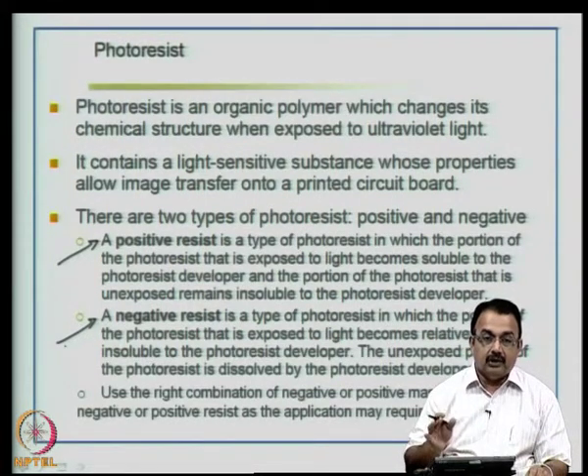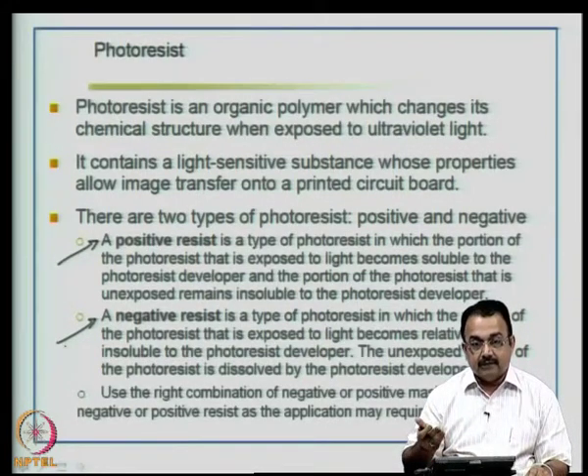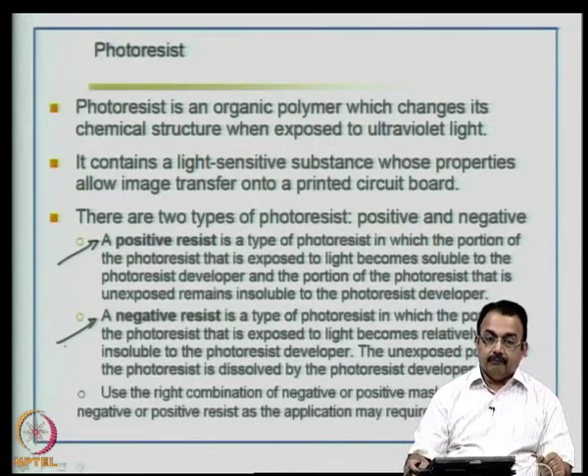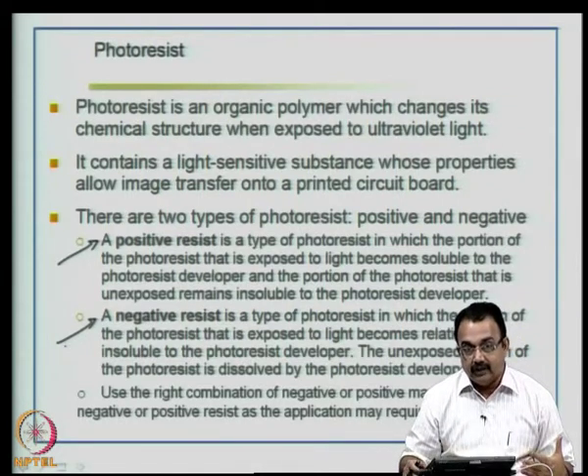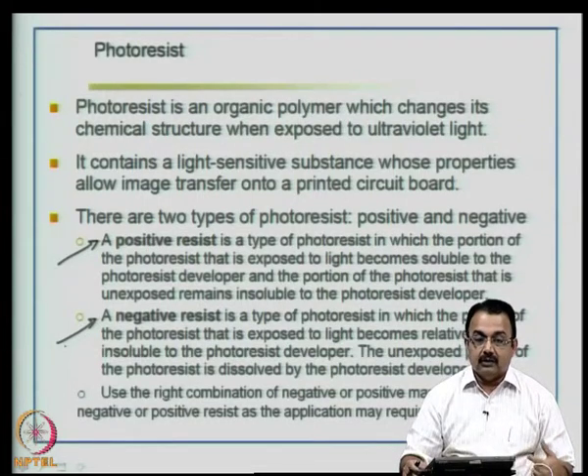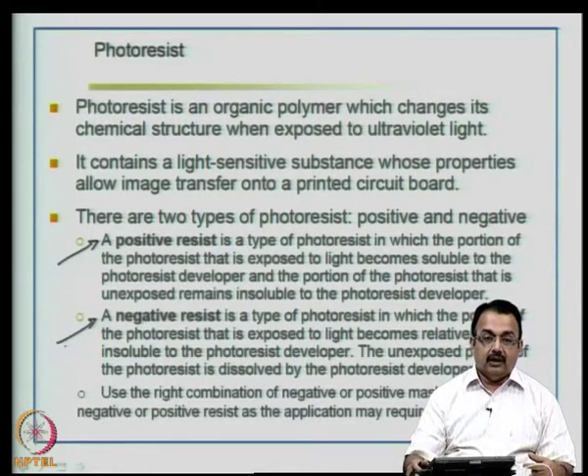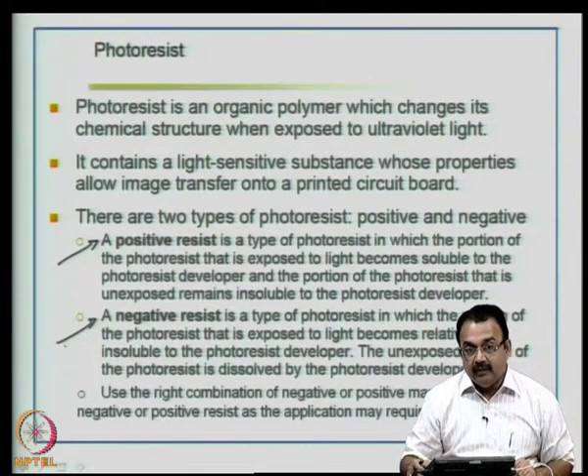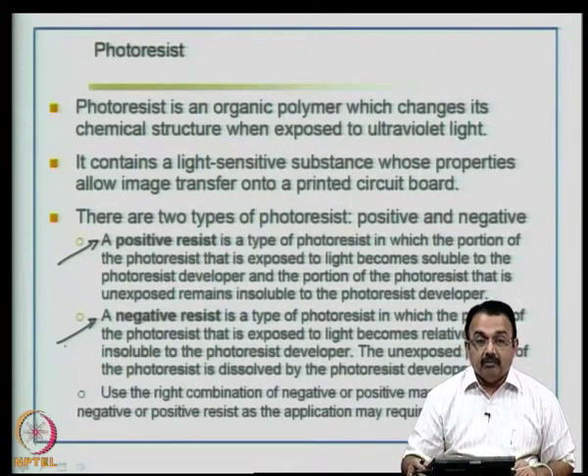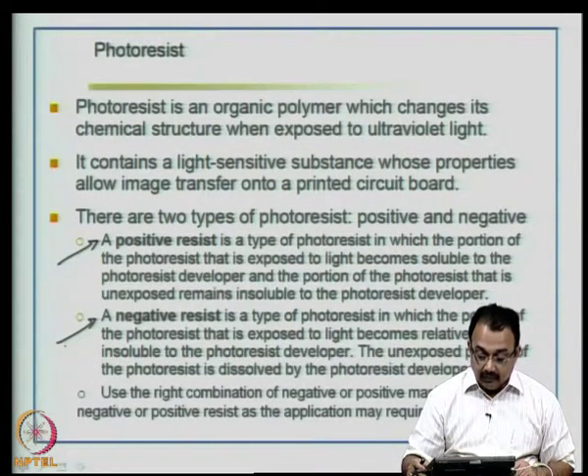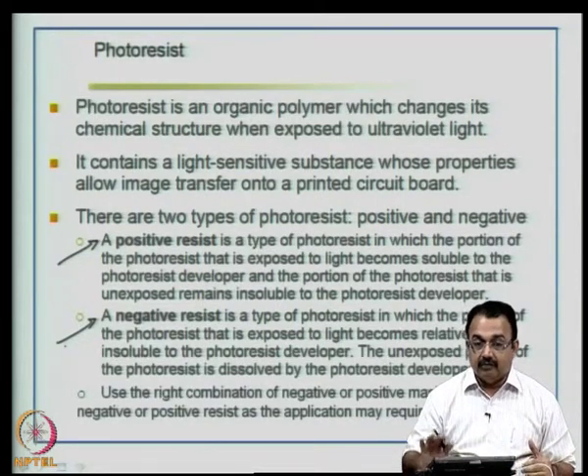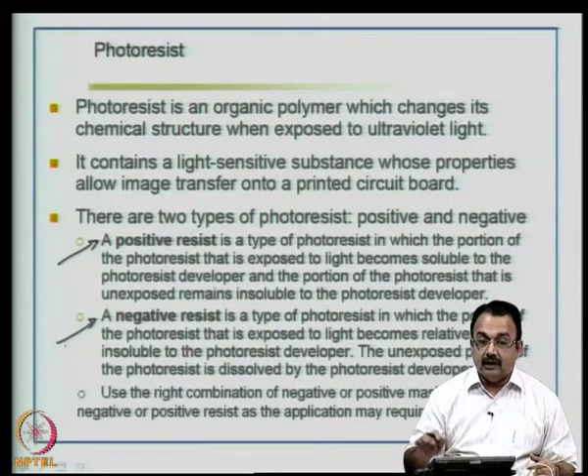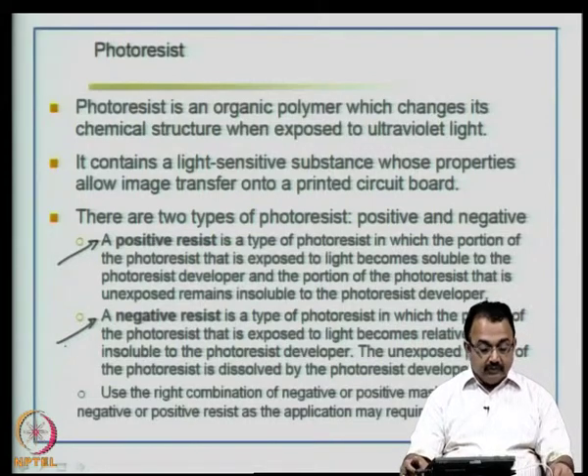Using the right combination of a negative or positive mask with a negative or positive resist, you can achieve the kind of image required. In some cases, a positive resist may be very good for fine line circuitry while a negative resist is better for coarse lines. Depending on the sequence in your multilayer board fabrication, this technology is important for building micro-via structures and fine lines on boards. A negative and positive photoresist have different chemical properties when exposed to UV light, resulting in different solubility in the developer — use this very judiciously.